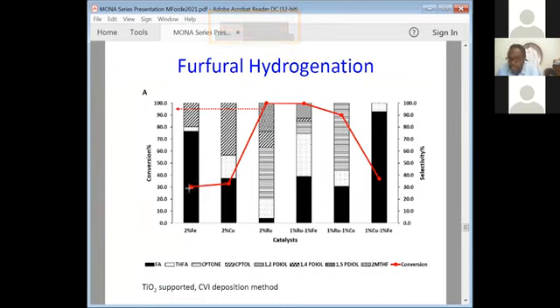This data is from my student, and she will soon be submitting her PhD thesis, I believe, sometime this year. And so this is her extremely good data. I'm really happy with this data, where she's taken ruthenium, copper, and iron, deposited on titania and also titanate nanowires, and was able to tune the selectivity. So here we see moderate conversion for ruthenium, high conversion, but look, too many things going on here. All of this is going on, too many products. When we start to mix these metals together, the selectivity profile changes. And so we could tailor what we're doing to make a particular product.